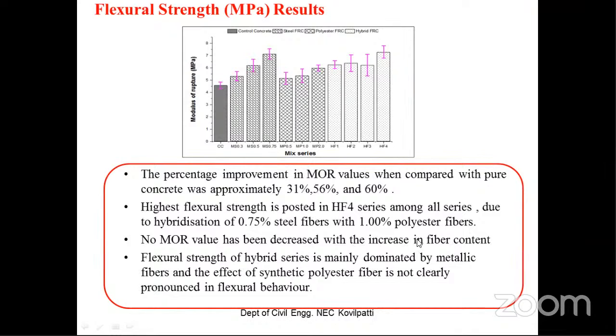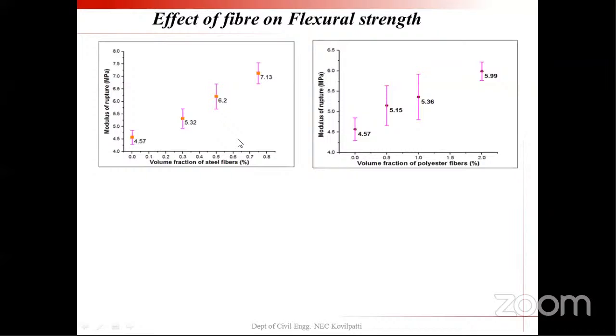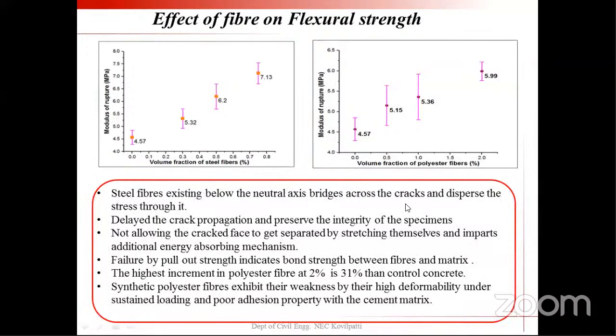In the previous two strength aspects, we observed some changes, but in flexural strength, with the increase in fiber content, the flexural strength keeps on increasing. We observed the hybrid series is mainly dominated by the metallic fibers, and synthetic fiber behavior is not much pronounced. This is a comparison made with the single fiber FRC for the modulus of rupture. Below the neutral axis, the bridge cracking mechanism is well defined, and it delays crack propagation. They preserve the integrity of the specimen, and fiber failure takes place by pull-out, which indicates good bond strength between the fibers and the matrix. And again, the synthetic fibers exhibit their weakness because of their low stiffness, high deformation and poor adhesion properties.